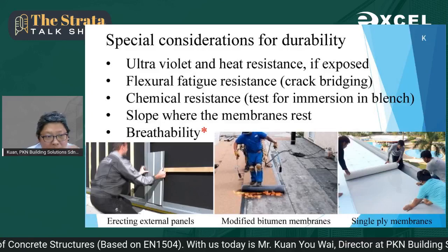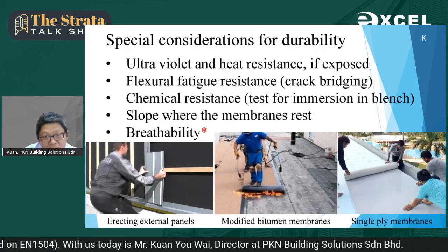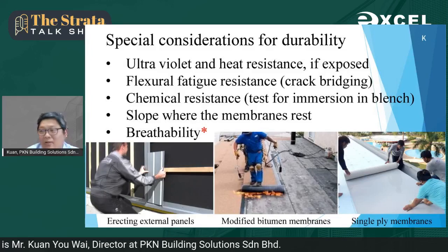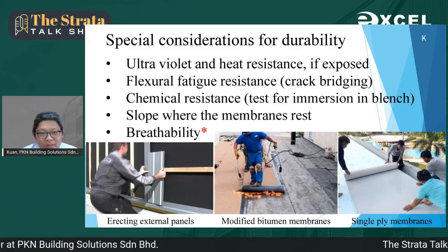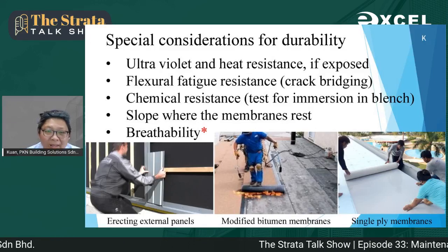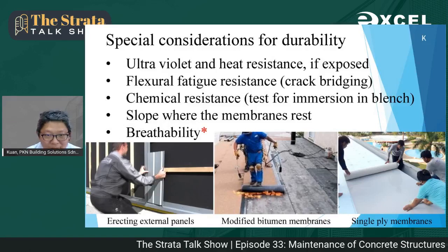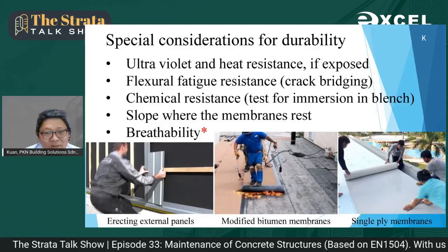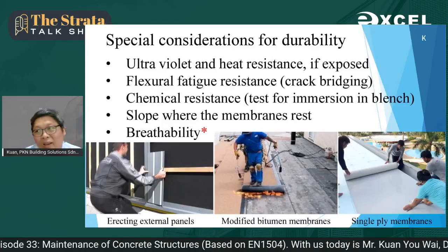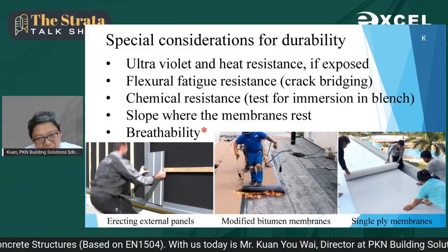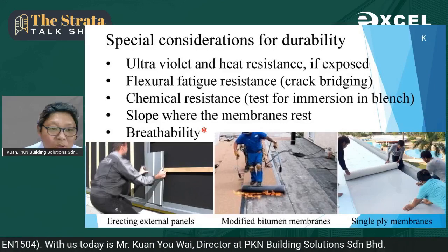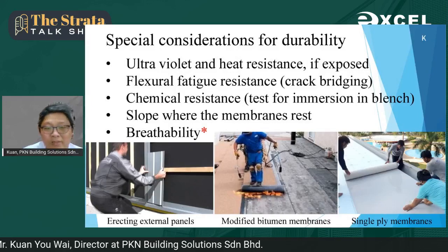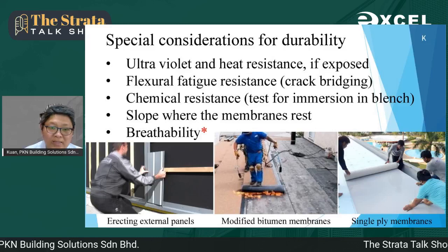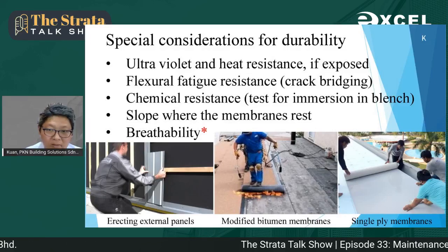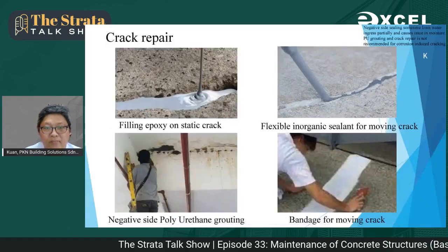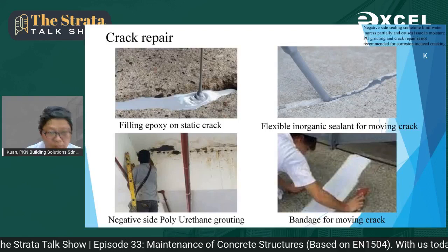Torch membrane, it has a layer of stone chips on the surface. It's black in color, and it actually is very good in absorbing heat, and the heat absorbed through the torch membrane causes further expansion to your reinforcement slab, the concrete slab. And as a result, the stress due to the expansion will crack the waterproofing or torch membrane on the surface. As a result, there are a few papers that say that torch membrane is not suitable for tropical. Single ply membrane is more suitable. And of course, water will flow through the crack.